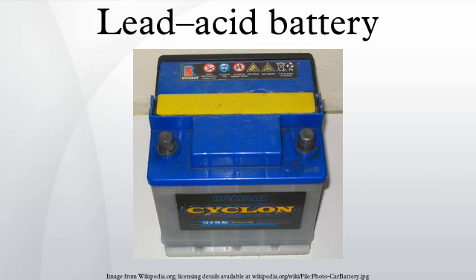Stratification: a typical lead-acid battery contains a mixture with varying concentrations of water and acid. Sulfuric acid has a higher density than water, which causes the acid formed at the plates during charging to flow downward and collect at the bottom of the battery. Eventually the mixture will again reach uniform composition by diffusion, but this is a very slow process. Repeated cycles of partial charging and discharging will increase stratification of the electrolyte, reducing the capacity and performance of the battery because the lack of acid on top limits plate activation.